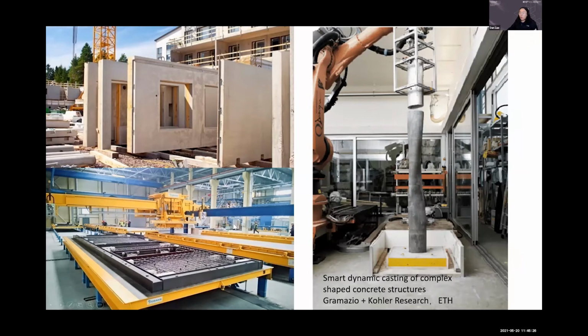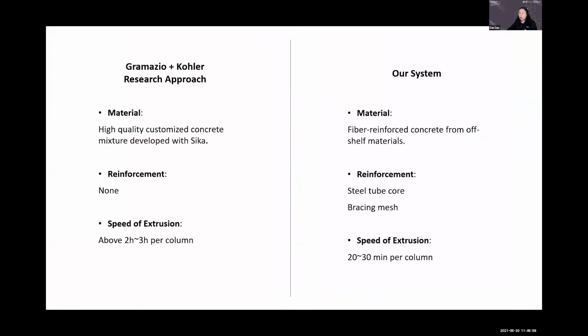One inspiration is from dynamic slipform casting, from the Gramazio Kohler Research group at ETH, where it's a migration between the typical slipform casting process and the additive process, so that the concrete is poured, cured, and pressured to deform with elastic deformation at each individual step of the extrusion. Based on this inspiration, we developed our own system that would accommodate the commercial application, especially for this project. One challenge is that we need to reduce the material cost, we need to add reinforcement, and we need to increase the extrusion speed compared to the prototypes that were developed in lab settings.